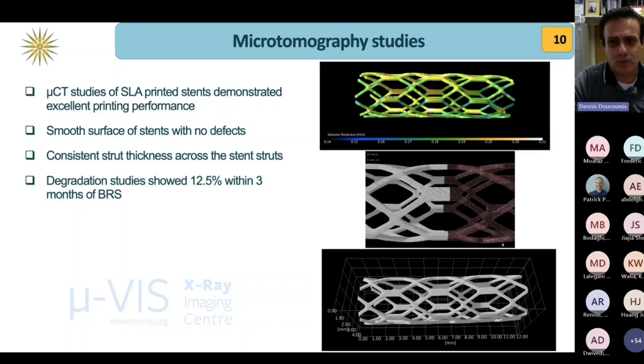So we ran some microtomography with some colleagues from Southampton University, and as you can see here, it gave us a good idea about the printing process. There were no defects or cracks on the surface. It was almost perfect and very consistent.